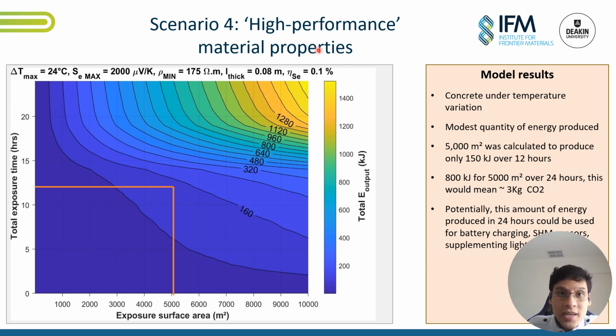But most importantly, if we look at the efficiency factor, if we increase it from 0.1 to 0.2, 0.3, these 3 kilograms can become 6, 7, 9 kilograms per day, 3, 4 tons per year, even 5, 5.5, just by increasing it a little bit. So imagine if we increase it by just 1% or 2%. That would cause a huge impact on CO2 offsetting.